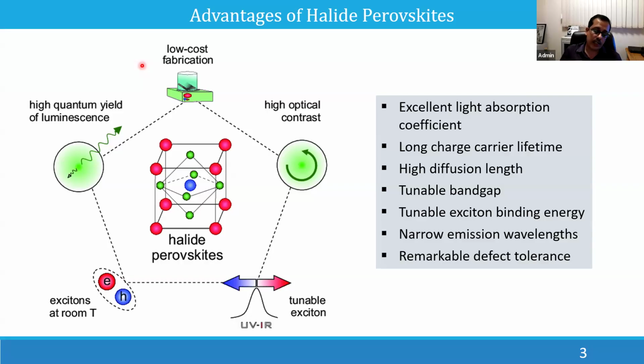Like if you want some application in the UV region, in some cases in the visible region, and in some cases in the NIR region, you can easily tune the exciton to that particular region by simply changing the structure of the material. And you can generate excitons at room temperature. Electron and hole can be generated at room temperature.